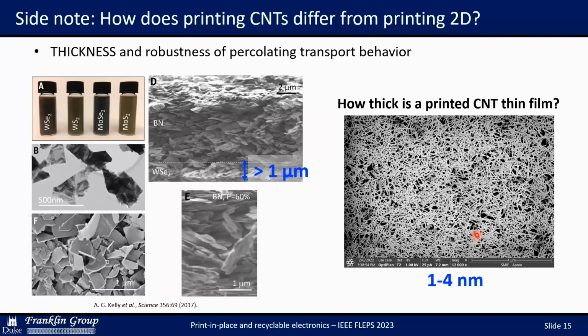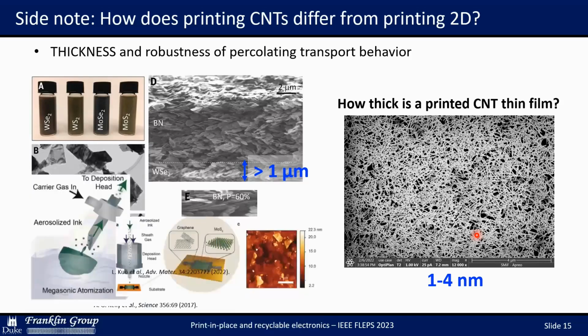Nanotubes, on the other hand, actually print into near monolayer films. And that's one of the advantages that can be utilized even when you're in a micron scale thin film device. And you can see an example of a printed film there, 1 to 4 nanometers in thickness.